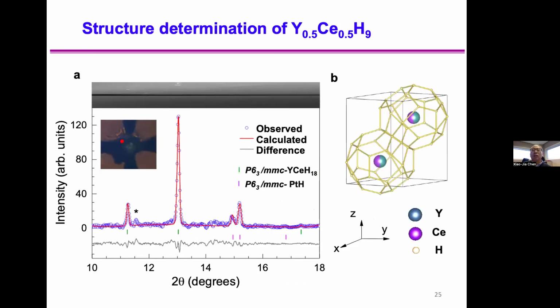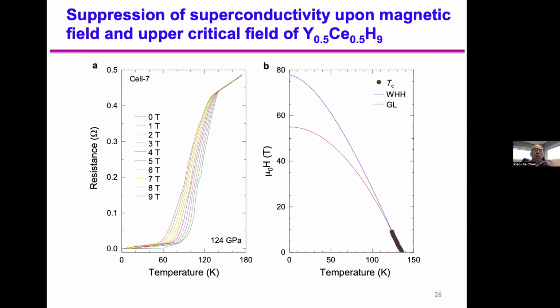For yttrium cerium H9, we also have the diffraction. Diffraction gives you a cage feature as well. Here we show the resistivity measurement with the magnetic field. You can see when you apply the magnetic field, the resistance is suppressed, the transition gets wider, and we can determine the applied field here.